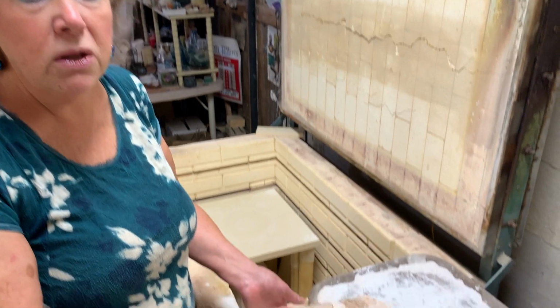Probably what I find the most useful use of alumina hydrate is to work as ball bearings, essentially, in a kiln where I'm trying to fire a flat piece. As pieces heat in the kiln, they have to shrink in a little bit, and if they hang up on a kiln shelf, it's more likely to crack. And so I've discovered that I can fire flat pieces pretty easily as long as I use my alumina hydrate.